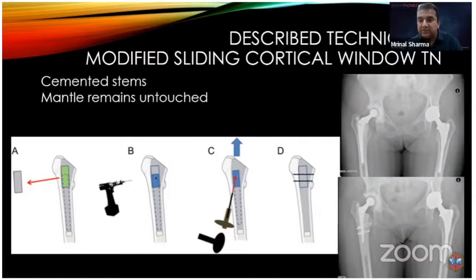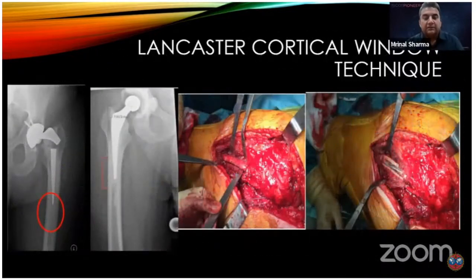The mantle remains untouched. You can see the proximal fragment of the stem here is broken, and they've just made a cortical window anteriorly. They have slid the distal part of the stem out, and the cement mantle is intact. It has been revised with a cement-in-cement revision, and the cortical window has been closed with cerclage wires. There's another technique called the Lancaster cortical window technique, where there is a broken proximal stem, as you can see here, and a lateral window is made almost 100 millimeters from the tip of the greater trochanter. It is laterally placed, and it helps you to approach the tip of the stem and also the cement plug distally, and you can just remove the stem and push it out in a retrograde manner.